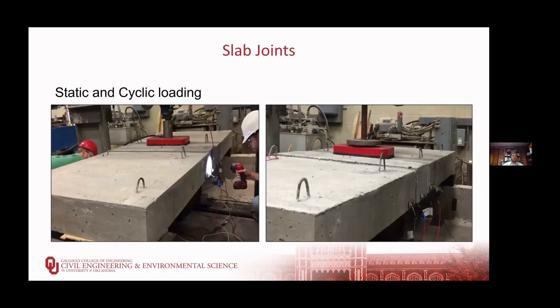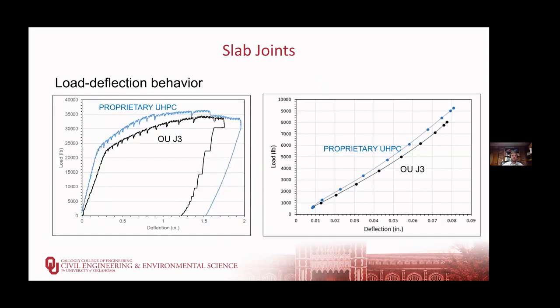We also looked at some full-scale slab joint testing. We did both static and cyclic loading with elastic level loads to simulate traffic. These were near full scale. And our load deflection behavior showed that we had a slightly less stiff specimen using our non-proprietary mix than with the proprietary UHPC, but we had very similar ultimate capacities, and we did have relatively similar stiffness. The OU material is a little less stiff than the proprietary UHPC in general, and the bond to the conventional concrete is not quite as strong.